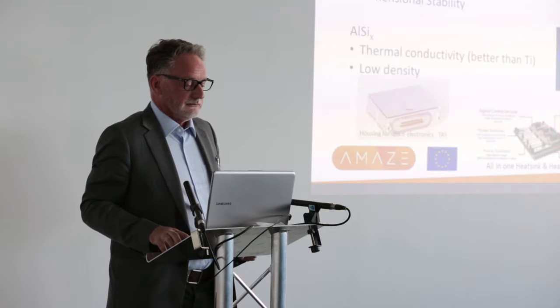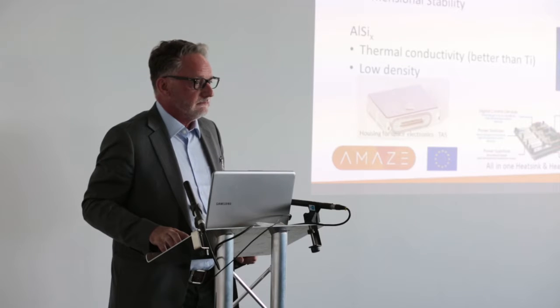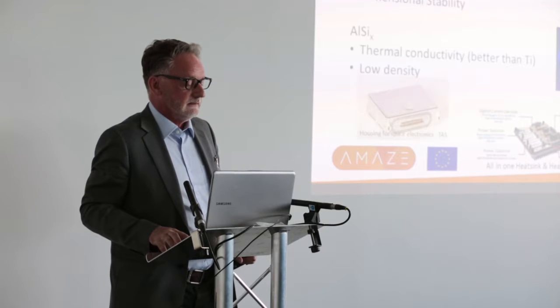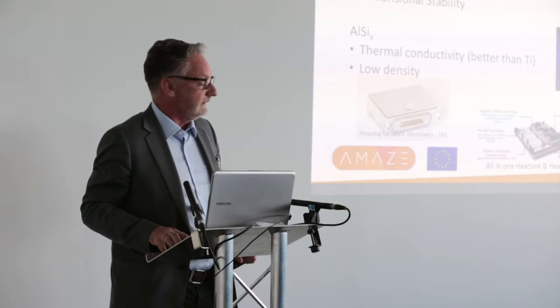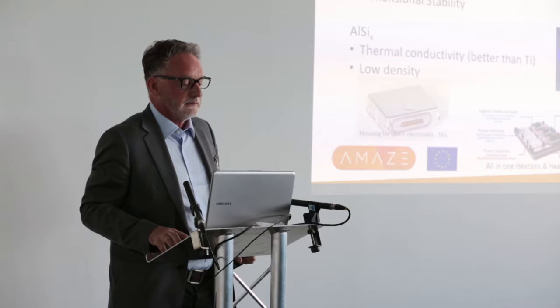In aluminium silicon X, you also get good thermal conductivity, which is often important for managing heat in spacecraft, and it has a much better thermal conductivity than titanium, which is currently used as a low CTE material, and it also obviously has a low density.